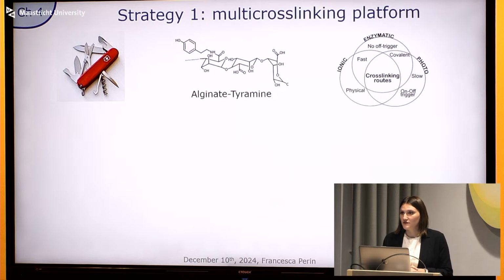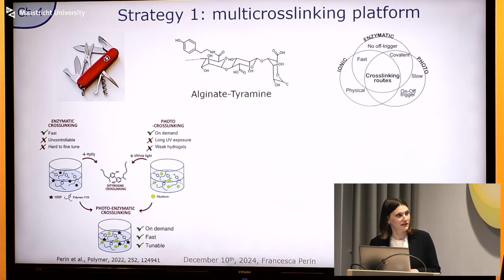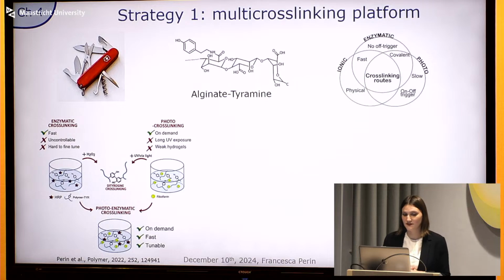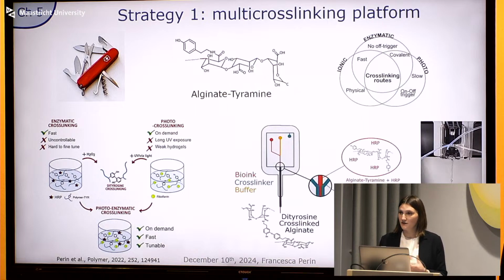Alginate tyramine can be cross-linked in different ways, both ionic and covalent, and via different reactions that give it quite a big adaptability in terms of biofabrication, because they have different triggers and different kinetics. So we did play around a little bit with the cross-linking and also managed to merge the best of both worlds of the enzymatic and the photo-cross-linking into a cross-linking that we called photoenzymatic, and that could be printed with extrusion bioprinting. And then to demonstrate that this was adaptable to a different technique, in chapter 5, we decided to print it with microfluidic bioprinting.